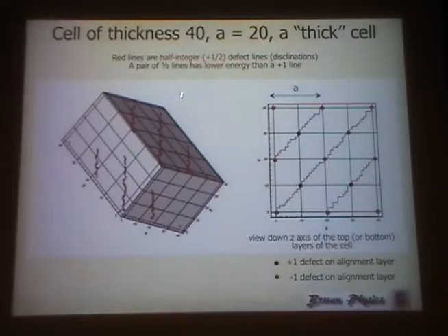Okay? And the other thing that happens that's worth noting, given your earlier lectures on topological defects and disclination lines, is remember these dots here are plus and -1 integer defects. Yet what we see happening is, rather than creating +1 lines and -1 lines, those things actually immediately bifurcate into 2 half-integer lines.